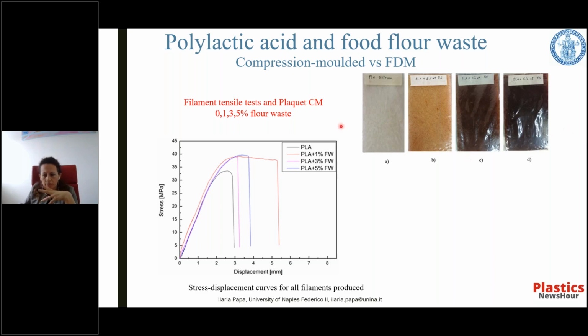As you can see in this graph, you can see the behavior of the innovative filament that we have produced during our research of all the materials extracted, and the filler promotes, as you see by this graph, a significant increase in material strength, but in particular, this effect holds true for specimens obtained by compression molding, but appears to be reversed when the filaments are transformed by FDM due to the important issues correlated to the innovative technology.